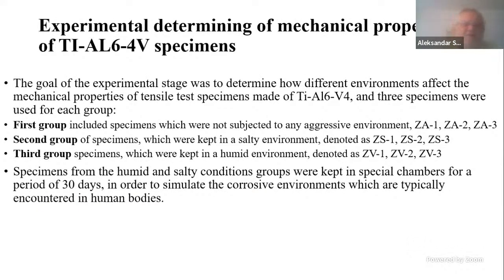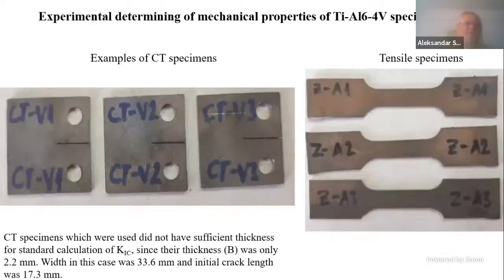This is already said. Just to additionally inform you that these chambers were used for 30 days to get humid or salty conditions. And then testing, of course, was not done in chambers, but in a normal laboratory. So here you can see these specimens. CT specimens were used for KQ and of course for Paris law coefficients. At the same time, we also tested tensile specimens to see the effect of the human body on tensile properties.